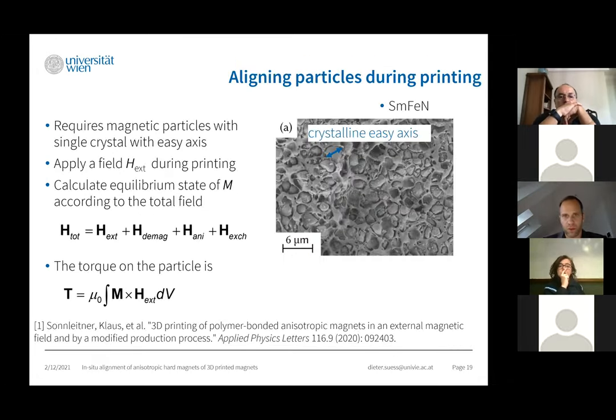But now we want to go a step further, and I'm going to talk about these new results where we used also single crystals, and we used samarium iron nitride as well as hexaferrites, where each particle here now consists of a single crystal. And if we have now a single crystal, we have a preferred magnetization direction. And if we apply a field together during the printing process, we potentially can align it.